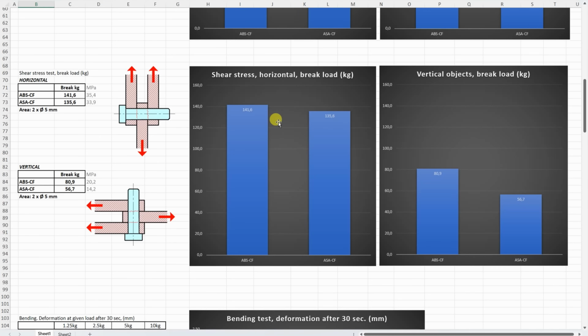With horizontally printed test objects, no big difference, but in both cases very strong materials, so these fibers help in this test. With vertically printed test objects, well, we can see that weakness of the layer adhesion with the ASA part, but this is also acceptable.